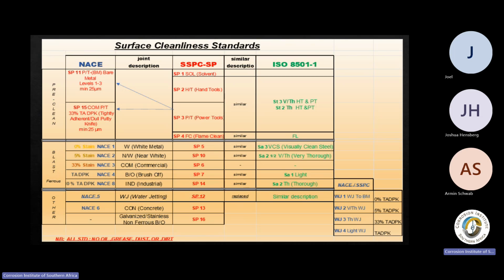So going back to the standards again, you can actually follow these standards, WJ, water jetting to bare metal, very thorough and light water jetting. And they specify the amount of rust back that you are allowed on the surface, either being light, moderate, or heavy. As soon as it's heavy, you don't put a coating on. You want light to moderate. That's where the paint sales guys will tell me they don't want anything more than a moderate. And you test it with a cloth. You take a white cloth and you wipe it over the surface. If you see rust on the cloth, it's not going to stick. That's too heavy. You need to move it over the surface so you see minimal flashback that actually comes back onto the little cotton swab.